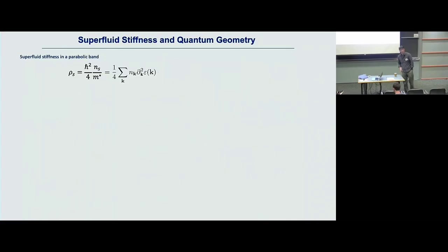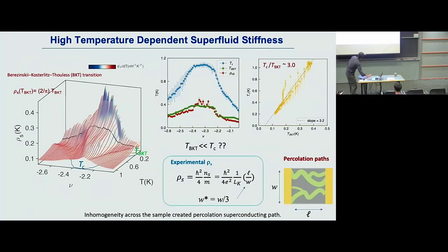Yes, yeah. And if you show, please, the data of the superfluid stiffness measured by the kinetic inductance, and if you plot the critical line, I really don't see this clear jump. That's right. So I'm more prone to follow this percolation path proposal that you mentioned, and in general, that kind of shape, at least in my experience, is more likely to be a signature of filamentary superconductivity, of having some sort of inhomogeneous superconducting condensate.